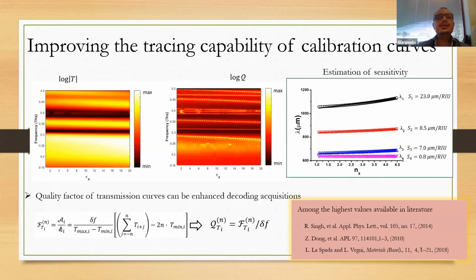And this is clear in this slide. In this figure, log of the transmission, we have studied the way the modulus of transmission changes according to the dielectric constant of the analyte. As we can see, these peaks in this contour plot are now quite wide, and following the change, the movement of these peaks, is quite hard in this case. Therefore, we have developed a simple code that studies the derivative of the area underneath the transmission peaks.